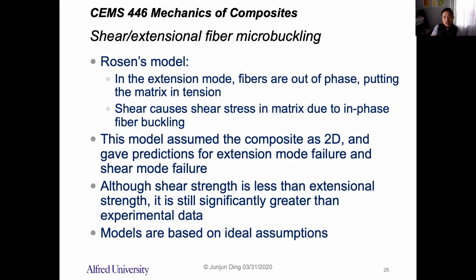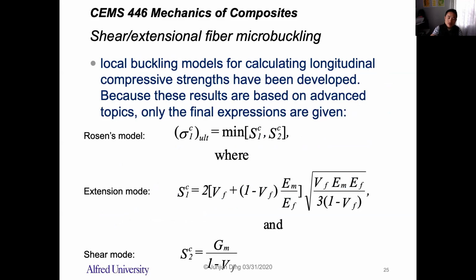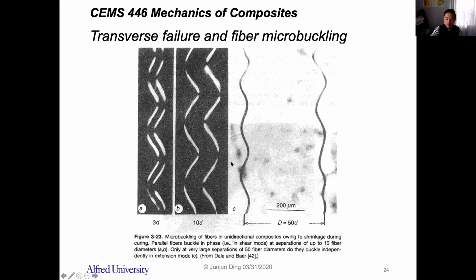So in this Rosen's model, in the extension mode, the fibers are out of phase, putting the matrix in tension. So the shear stress in the matrix is due to the in-phase fiber buckling. So this shear mode is because of the shear stress applied in the matrix in between them. So here, this is the shear deformation applied to the matrix.